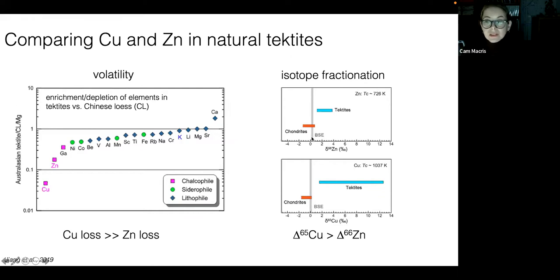What I'd like to point out, just a last thing, is that in the upper right-hand corner of these plots, the authors provided the half condensation temperatures for these elements. As geochemists, we regularly look to the half condensation temperatures of elements as an easy predictor of volatility, with lower temperatures indicating higher volatility. And that is in fact the exact opposite of what we observe here. So all of this data tells us that this practice of using half condensation temperatures as a guide for relative volatilities of elements may not be valid for all materials. These half condensation temperatures are calculated for condensation in a hydrogen-rich solar nebula gas at very low pressures, and they are likely not applicable to tektite formation in Earth's atmosphere.